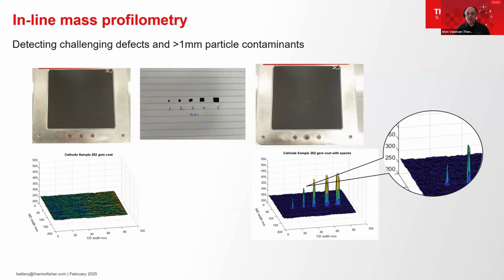Looking at the photo of the electrode on top, you can see larger flakes with some effort. The smaller flakes are much harder to see. They're nearly invisible. There is no color contrast, and the optical inspection system would struggle to detect this type of defect. The mass profilometry data, however, makes the flakes easily detectable. The difference in mass in the local area where the flake is placed is very large, and it is easily picked up by the system.